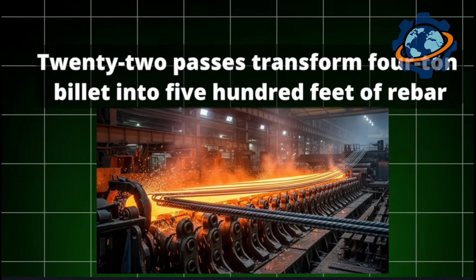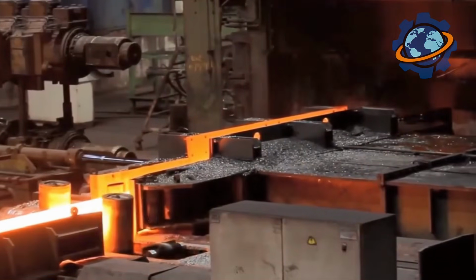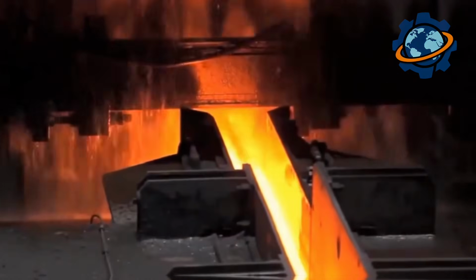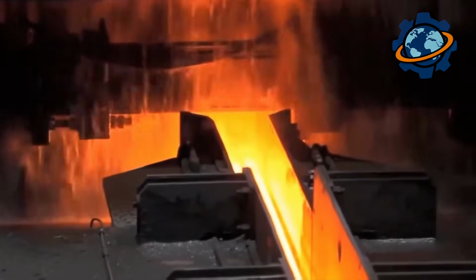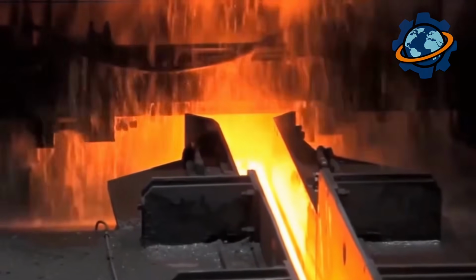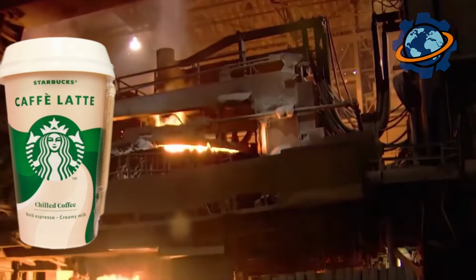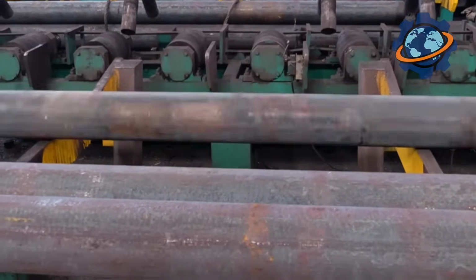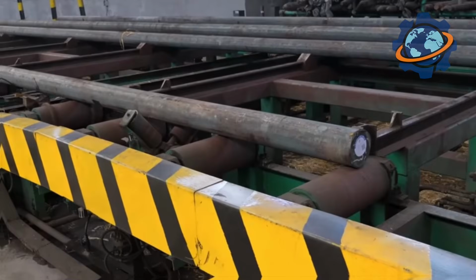But here's where rebar gets its identity: the ribs. Special roller dies emboss transverse ribs and longitudinal ridges onto surface. These aren't decorative. The ribs increase surface area by 40%, creating mechanical bond with concrete. Smooth bar would slip under stress. Concrete would crack and fail. Ribbed bar locks into concrete through friction and mechanical interlock.